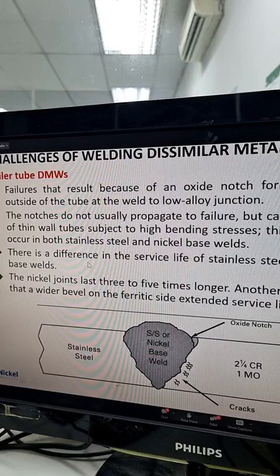So what they observed was the nickel joint was giving 3 to 5 times longer life, while the stainless steel joints, their life was very limited. Another finding was that a wider bevel on the ferritic side also extended the service life.